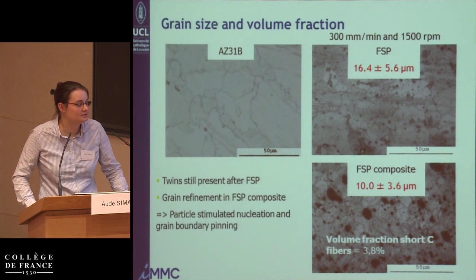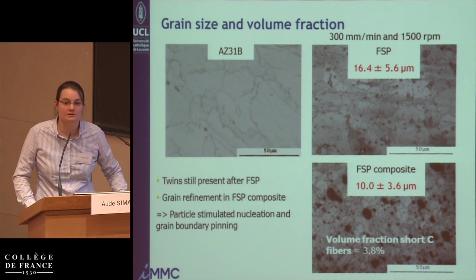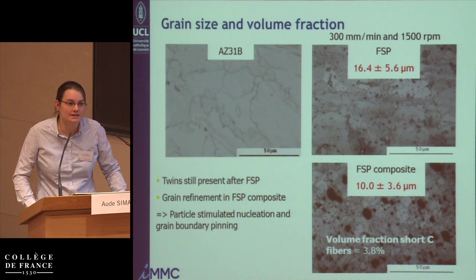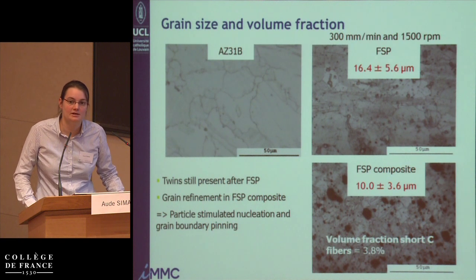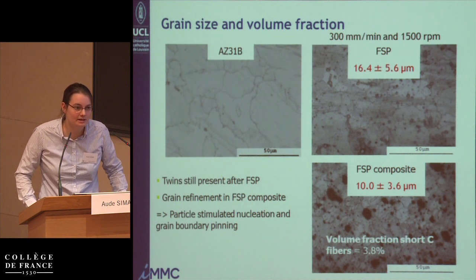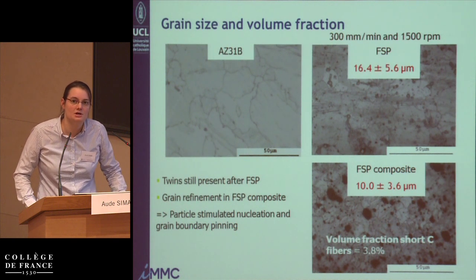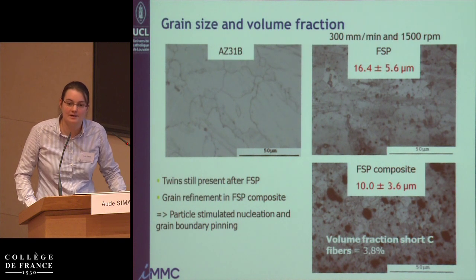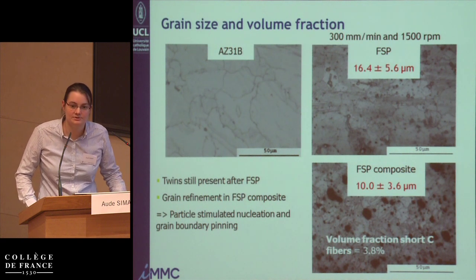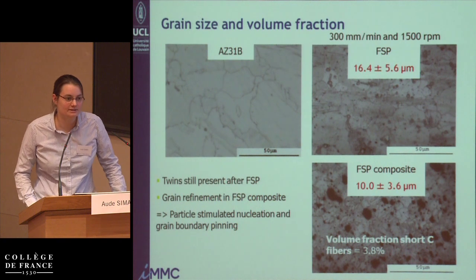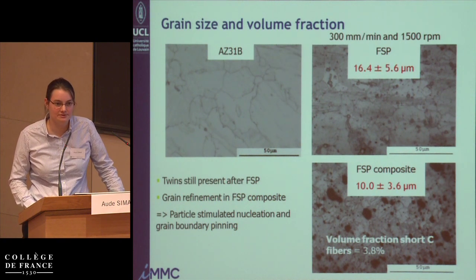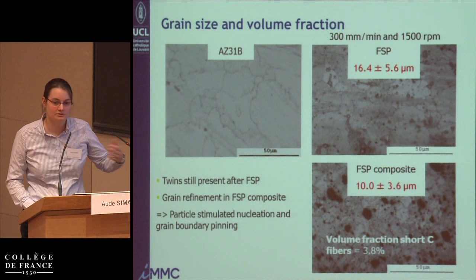And we have a volume fraction of carbon fiber that is typically 3.8% in these materials, depending on the parameters that we input. So we are already reaching larger volume fraction, of course, than we had for the nanoparticles, but we are talking about macro or micro particles here. But still, it's probably not sufficient compared to what you can find in volume fractions of carbon fibers in the liquid state process that I showed you at the very beginning, the squeeze casting, where there the volume fraction of carbon fibers is much larger, and hence you have a larger effect of the carbon fibers.